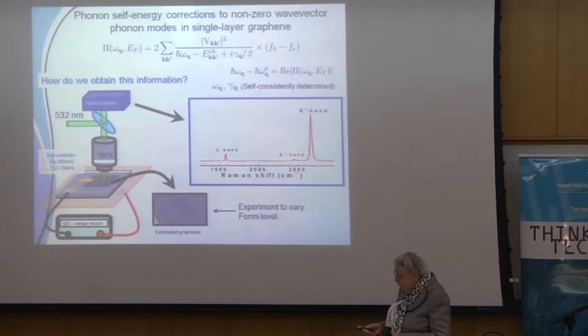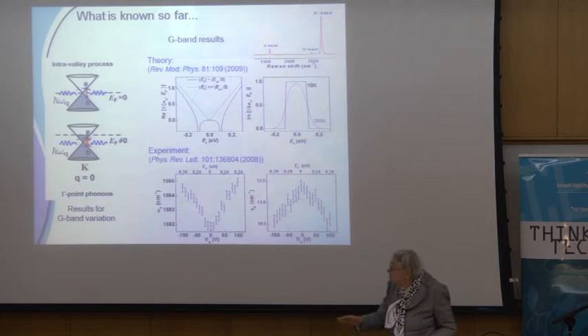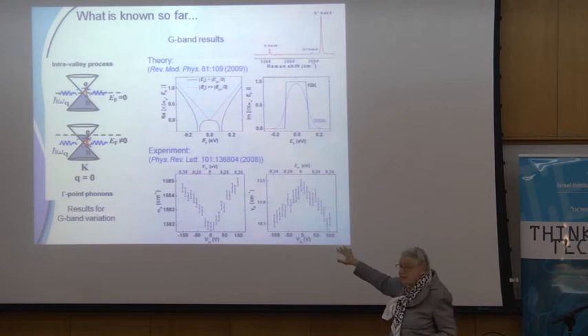And so, for example, here, we vary the Fermi level, that is the position of the occupation of the valence and conduction band, by changing the voltage applied to the graphene. For example, we could move the Fermi level up into the conduction band or down in the valence band. So here's the technique that's done. We have gates, we call them gates, shown over here. So this is the ground, and here is the voltage on the sample. And so we could look at, here's spectral features, and we can move them around, and that's the kind of research that we're doing nowadays. And we study with all these different features how they change their energy and momentum as we change the energy level, the Fermi level. So we fill electrons and we fill holes, and we watch what happens to the transition.